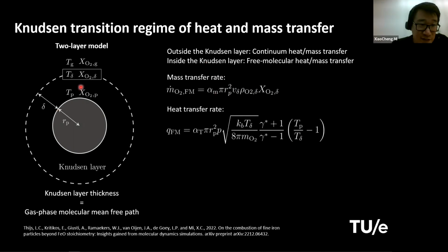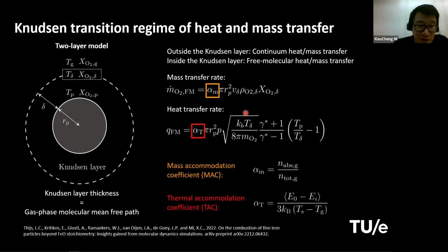And as I said, inside this layer, the mass and heat transfer rates are calculated using the free molecular regime's heat and mass transfer model. This looks different from the continuum heat and mass transfer model. You can remark there are two important parameters here, which are the mass accommodation coefficient and the thermal accommodation coefficient. The mass accommodation coefficient measures how many of these molecules can be absorbed into the particle, divided by the total number of molecules colliding with the particle.